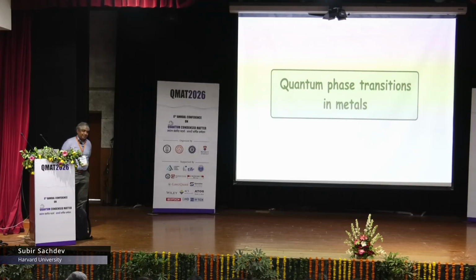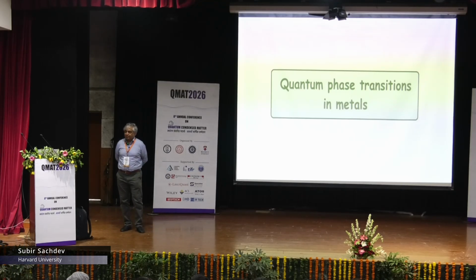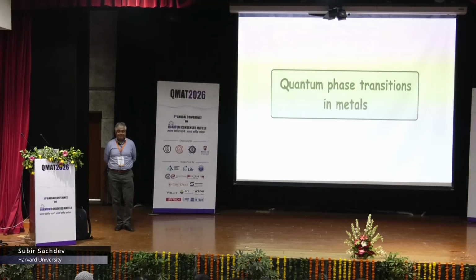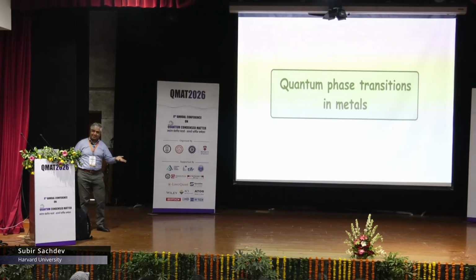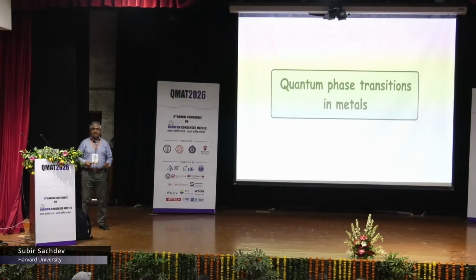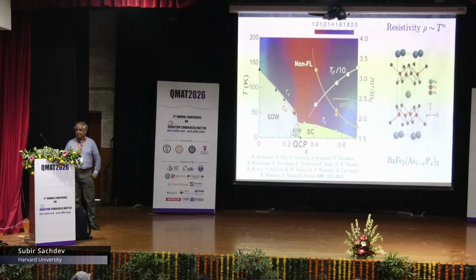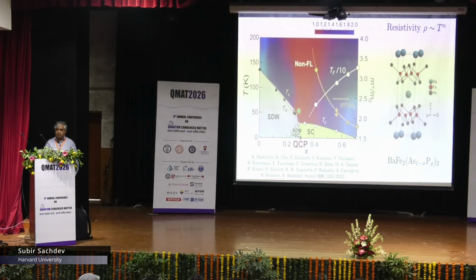Okay, all right, so let's get back to the cuprates and give you an update. So for a few minutes, I'm going to not talk about the SYK model, even though it's my favorite model. But I'll talk about another favorite subject of mine, which is the subject of quantum phase transitions, but phase transitions in metals. And that's another valuable framework in which many, many different materials in correlated electron systems can be understood. So here I show the phase diagram of this pnictide compound. It has a much lower Tc, 30, 40 Kelvin. But it also has this phase here, spin density wave, which is basically a regime where the spins are in some staggered antiferromagnetic arrangement. And what you see here is, first of all, there's a strange metal, like in many, many materials. It's right where you have the maximum Tc, like in many, many materials. But you also have that the spin density wave seems to vanish at some kind of quantum phase transition here within the superconductor.